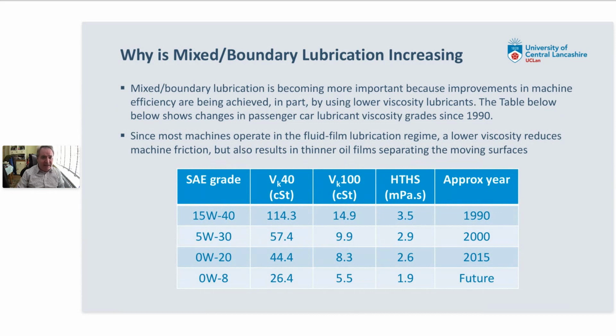If we go to the present day, a lot of people are using 0W20 grade lubricants in their cars nowadays, and the viscosity has effectively halved at 40 degrees centigrade, has come down by about a third at 100 degrees centigrade, and has come down substantially at the high temperature, high shear viscosity. So the reason why people have been using lower viscosity lubricants is because engines are primarily lubricated hydrodynamically. So if we reduce the viscosity of the fluid, we should reduce the friction in the engine and improve the fuel consumption. And that indeed is the case. But one of the ways in which the friction is reduced is by having a thinner film. And so there's more chance of mixed and boundary friction occurring, particularly at high loads and low speeds and stop-start conditions.